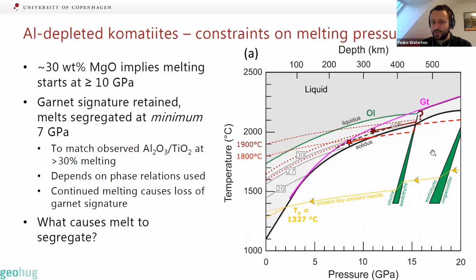So on the figure on the right, you can see this is a temperature pressure phase diagram for the mantle. You can see present day ambient mantle, and note that there are these little steps in the major mineral transitions. And the present day mantle has a potential temperature of about 1300 degrees C. If we move back to the Archean and much, much higher potential temperatures, if we have a potential temperature around 1800, this will cross the solidus at around 10 or 11 gigapascals, giving us our 30% MgO. And it can just about reach the 30% melting curve before we hit this garnet out line. So therefore it's possible to generate a komatiite with low aluminium over titanium and very, very high MgO with high degrees of melting and keep that garnet signature.